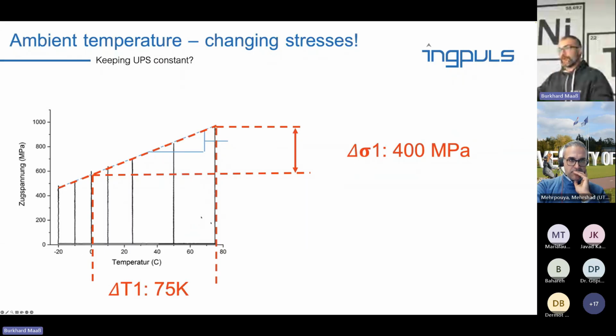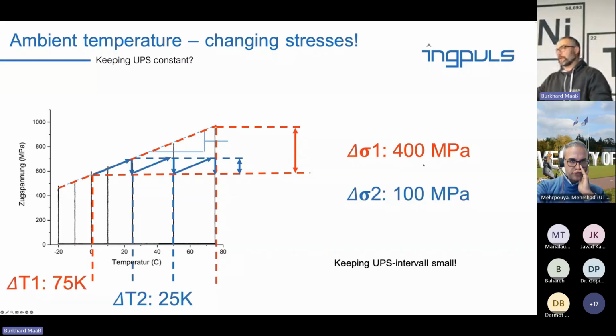So here, if we look at the delta T from 0 degrees to 75, we have a delta sigma of 400 megapascal. And an idea would be, if we can now come with different materials which are compensating for the Clausius-Clapeyron, we start at a lower first plateau stress, and then as we go higher with the temperature, the next material state kicks in. And this is how we could have a smaller delta sigma. And this is what we wanted to try out.